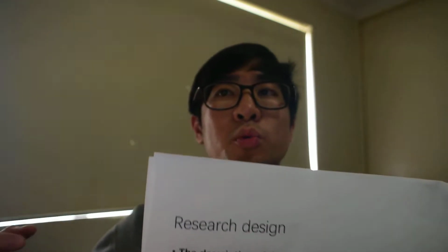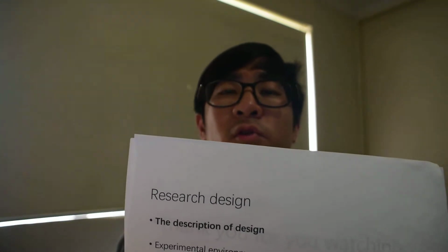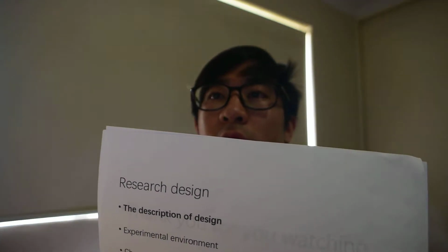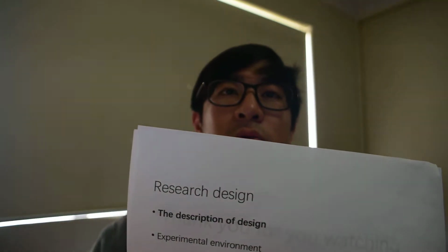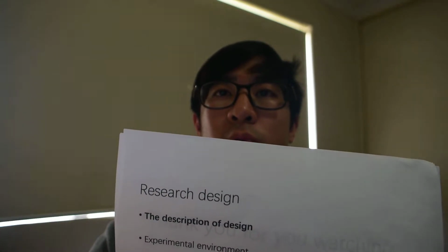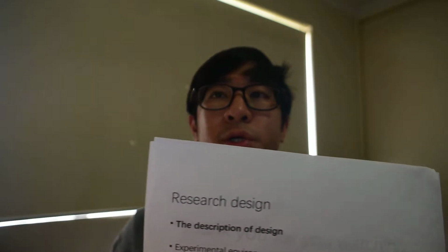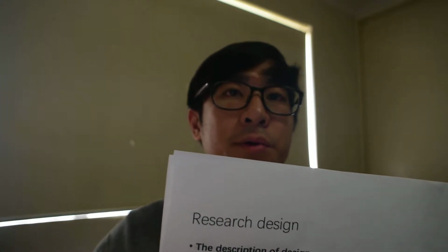This experiment will establish a control group and experiment group. The first group used the NSM FRP method, and the second group used the EB FRP method. The 2 groups were exposed to the indoor temperature, 400 centigrade and 600 centigrade for 3 hours.